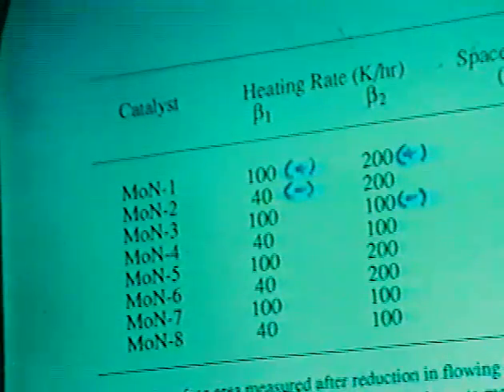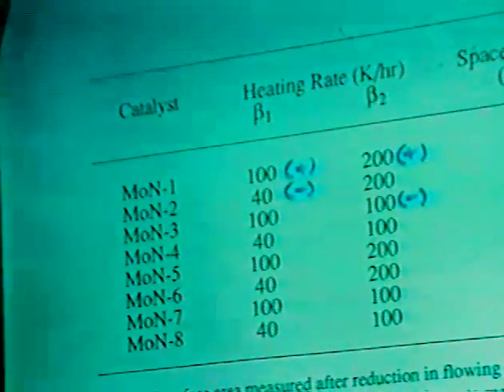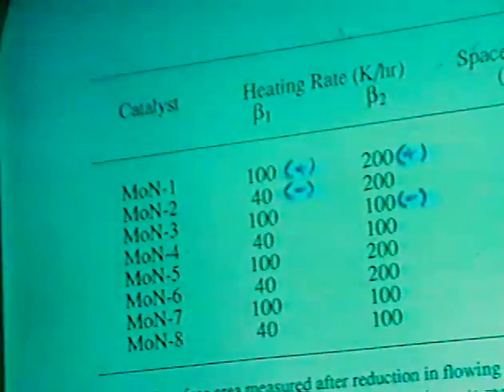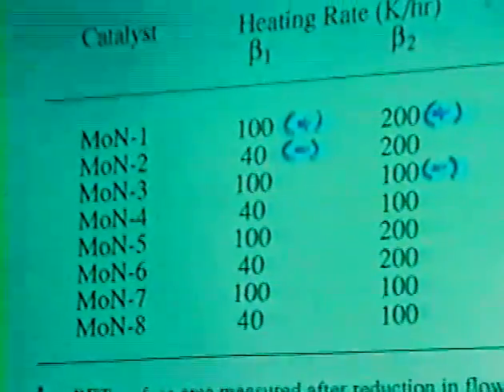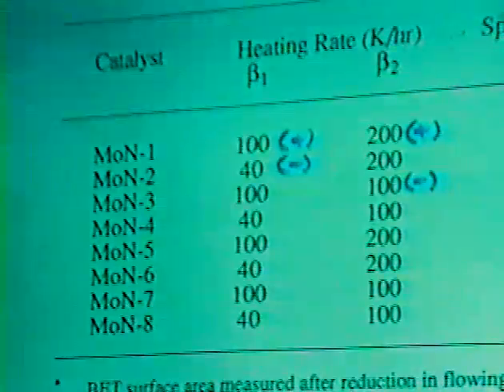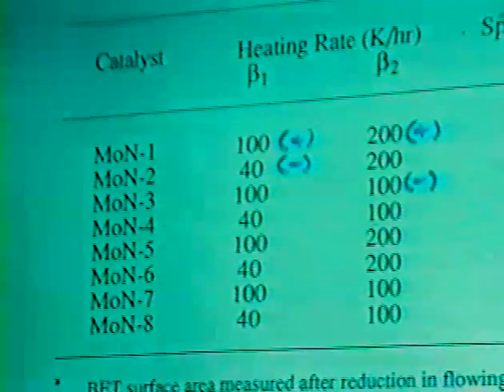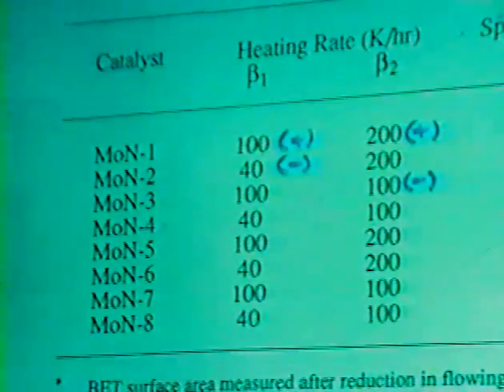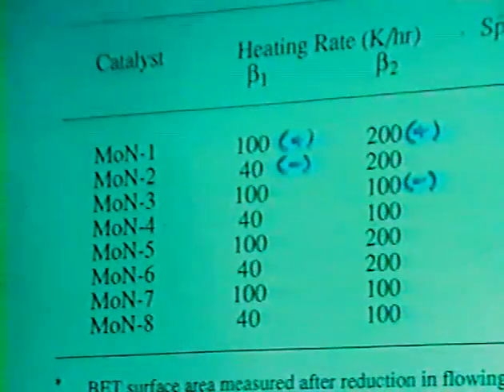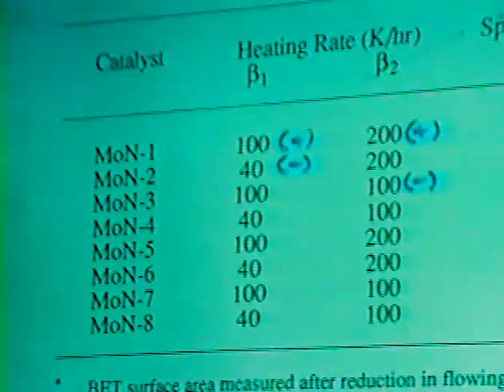You'll notice that, for example, when comparing 1 and 2, the only difference between the 2 of those experiments was the first heating rate that was employed. So this experiment would allow us to determine whether the first heating rate has an impact on the structural properties of the material. Comparing 1 and 3, we can look at the influence of beta 2, and then 1 and 5, we can look at the influence of the space velocity. This is the simplest treatment of this data. There are statistical analysis packages that will allow us to, with a 2^k factorial design, determine coefficients or correlation coefficients for these results, and we use those as opposed to simple comparisons with only one parameter varied.